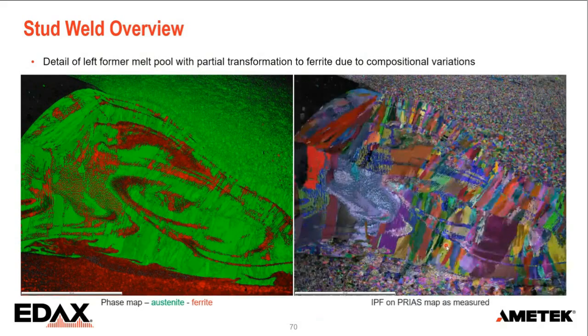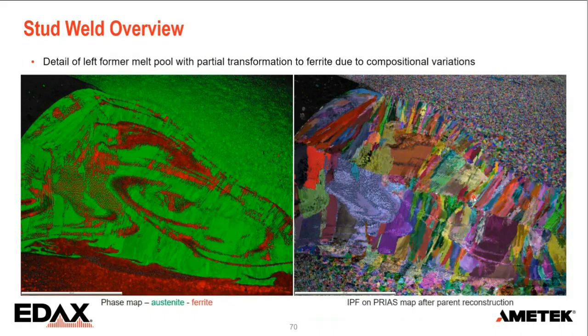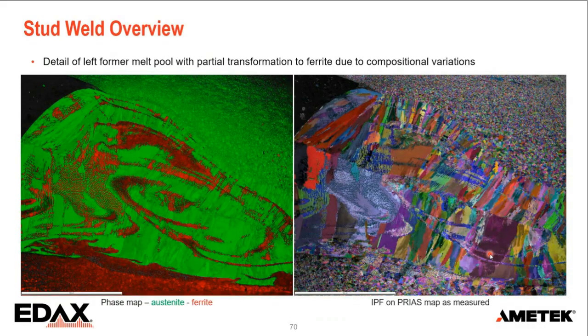We index that, look here at the IPF map. And we have all those small blue grains everywhere. That's the ferritic structure. And when we do a phase parent grain reconstruction there, we get this. So now again, you can see that this structure really crystallized as austenite, and only after cooling, part of that fell back into the ferrite structure based on the composition.